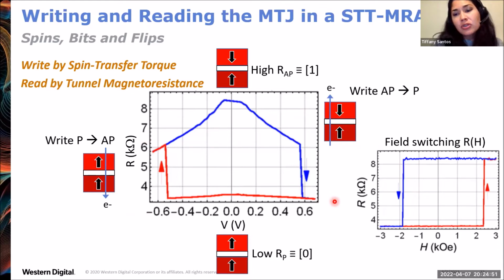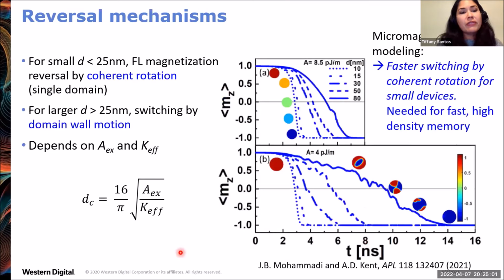So if you take the same tunnel junction and flip it by a magnetic field, this is what the transfer curve would look like. Okay, and this flipping of the free layer or the reversal can happen in a couple different ways. If the tunnel junction size is very small, for example, a diameter of 25 nanometers or less, then the flipping will happen by coherent rotation. So shown in these colors here, you start with all the spins pointed up and they rotate together as a single domain during flipping, and then facing downward with the magnetization in color blue.